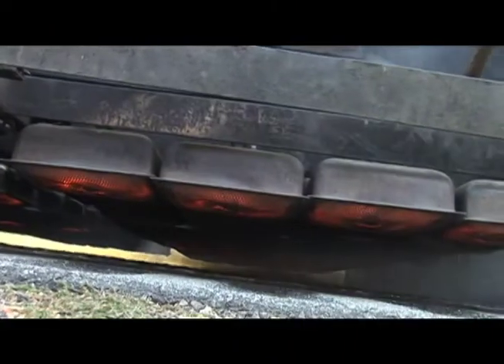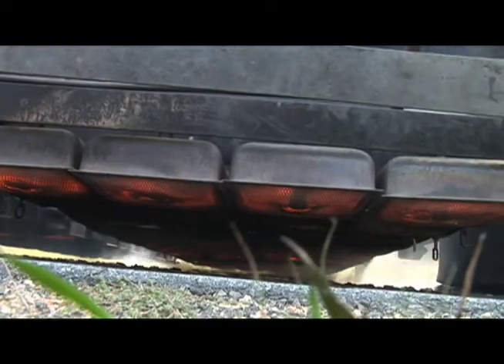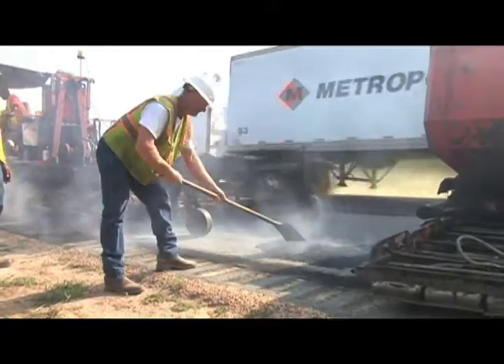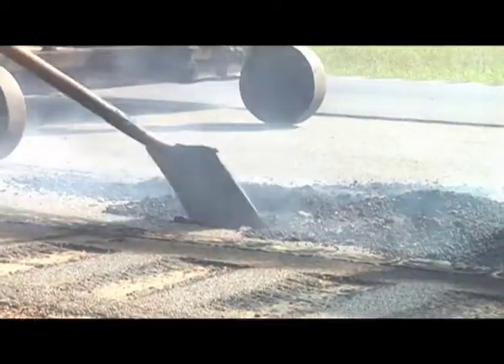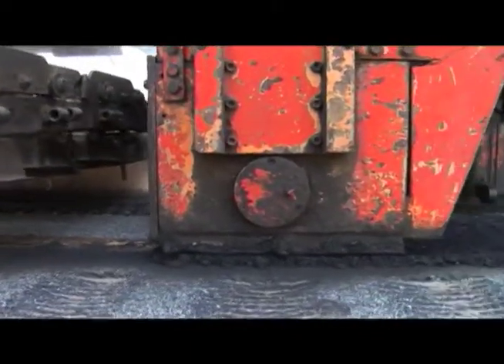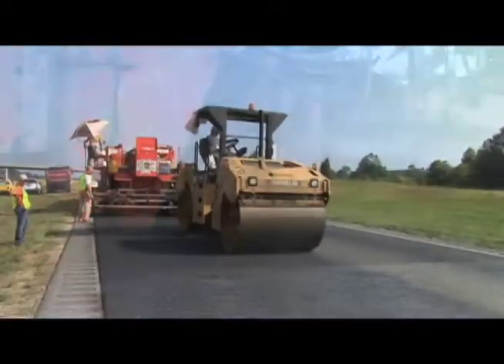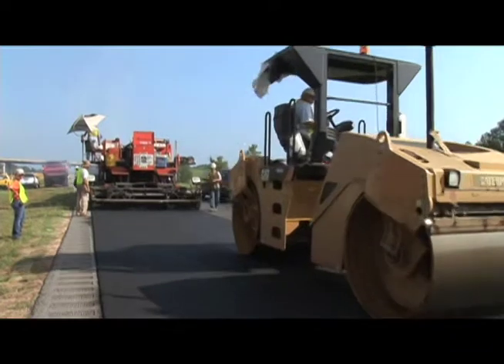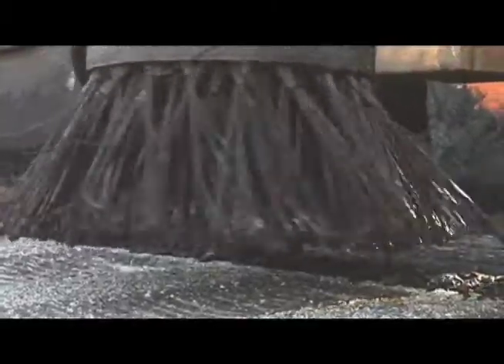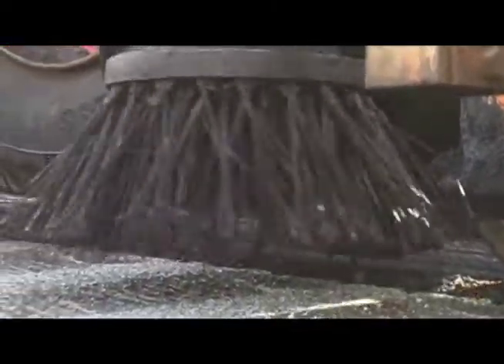Propane gas heating units utilize convection to transfer heat energy to the burners in the banks of the heating elements. Using these heating banks, the top one-and-a-half to two inches of the pavement riding surface is heated and softened. The heated and softened top layer of asphalt pavement is then milled and augured into the Hot in Place Pavement Recycling Unit. The remixed and recycled pavement is then laid and compacted at 225 to 230 degrees Fahrenheit. No tack coat is required due to the excellent thermal bond created between the remixed pavement layer and the underlying pavement surface.